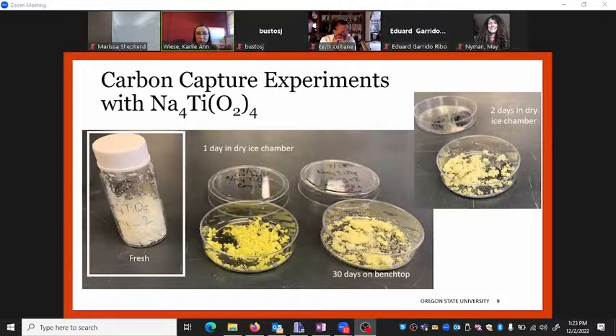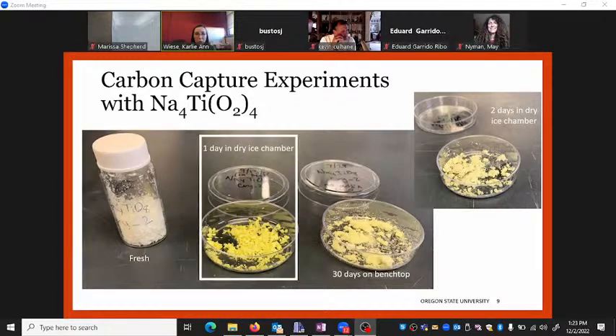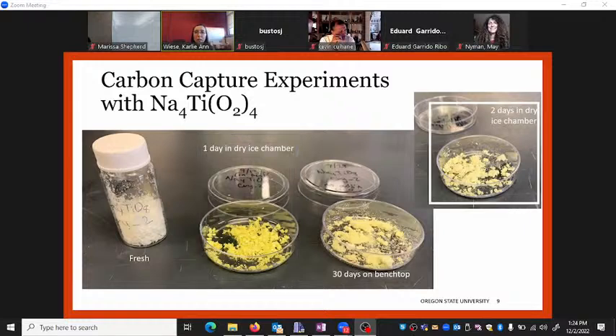So this is what the material looks like when it's fresh, when I synthesize it. One thing we do is place this sample into a chamber filled with dry ice. Dry ice is solid carbon dioxide, and at room temperature, it goes from being a solid to a gas. So the sample ends up sitting in a chamber of a CO2 cloud. After 1 day in the chamber of CO2, we notice that it changes from a white crystalline sample to this bright yellow. After another day in the chamber, it ends up being this pale yellow.